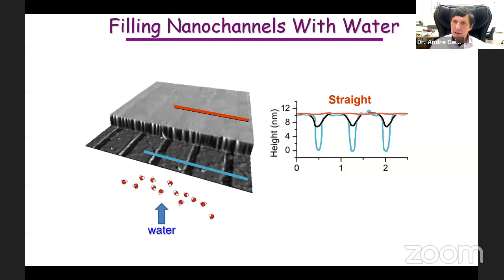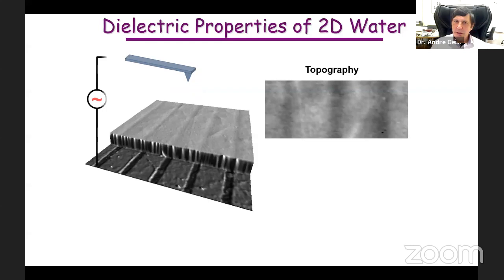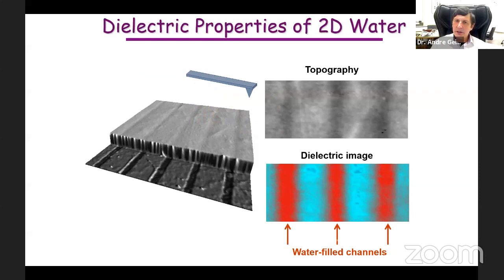This is our background. Now, after making this kind of topography image, we do capacitive measurements to see the dielectric properties of this assembly. The top is a dielectric hBN crystal, this is also an hBN crystal. The bottom is graphite, and we measure the capacitance between the tip and the bottom graphite, because water has a very high dielectric constant, about 80, as you know.